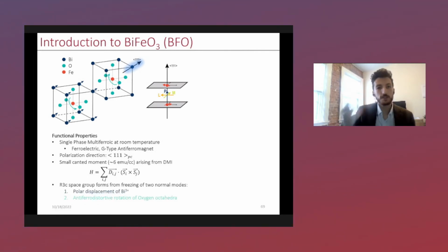However, this material is not hexagonal like hematite is. It's actually rhombohedral, which is also a derivative of the hexagonal crystal structure. And this mainly comes from the polar displacement that you see from the polarization, as well as very strong oxygen octahedral tilts in these systems as well.